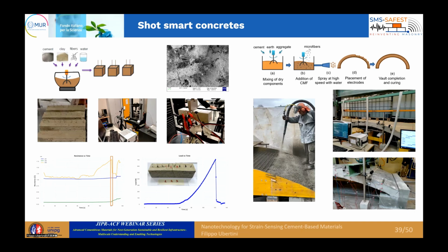Here you see, for instance, a tensile test in 3-point bending, where you see there is the failure in tension, and here you see that there is the jump in conductivity. So the material senses the damage.